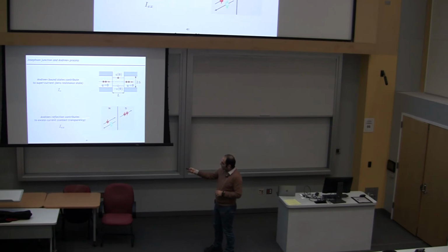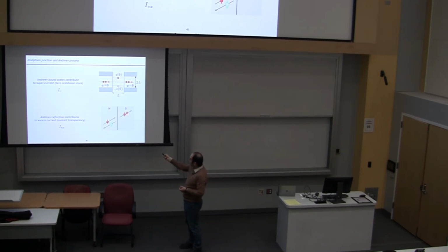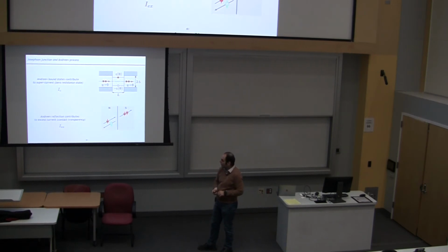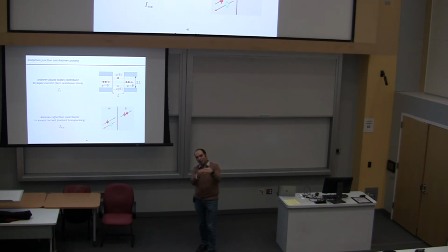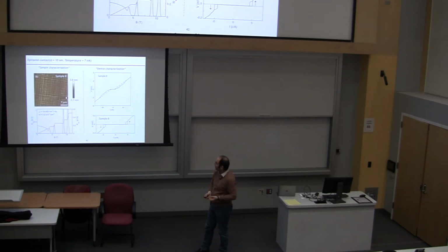And Andreev reflection is a one-sided effect. If you have one SN junction, you can get an excess current that comes from the extra contributions of this Andreev reflection, and basically gives you the contact transparency, right? All I'm arguing is that my interface is good, and I have to show you that by some measurement, right?